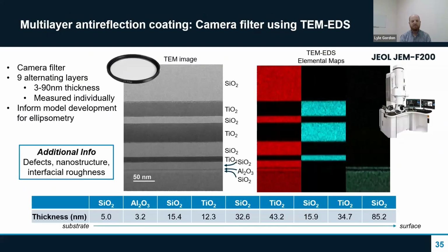So the next example is one that Max already showed in the ellipsometry example. This is a camera filter with an anti-reflection coating. We started this project and we actually didn't know what materials were used to make the coating, as well as how many layers we had. So starting from there, we'd simply be guessing at that. Using ellipsometry or X-ray reflectivity to model this would be really hard without knowing the details.